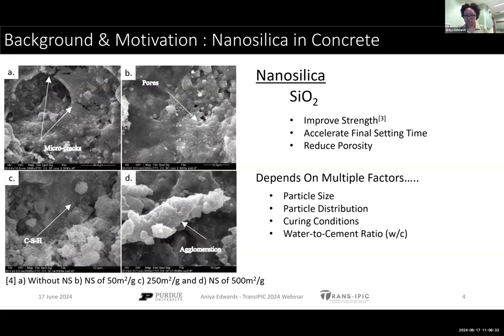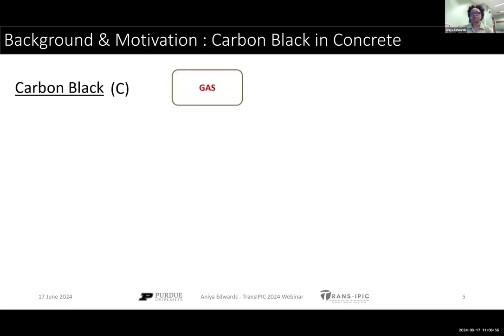Whereas without nanosilica, you can see some microcracking in the image A in the top left corner. So there's a sweet spot for what kind of nanosilica you want to use and what kind of surface area you want to achieve. And for them, it was found to be 50 to 250 meters squared per gram. So along with this, there's a lot of other factors. So it's a very multifaceted material that we're looking at when it comes to using it in concretes.